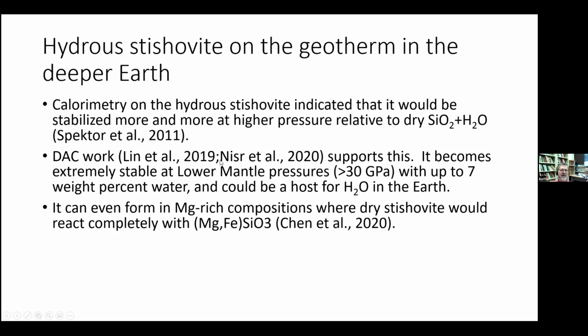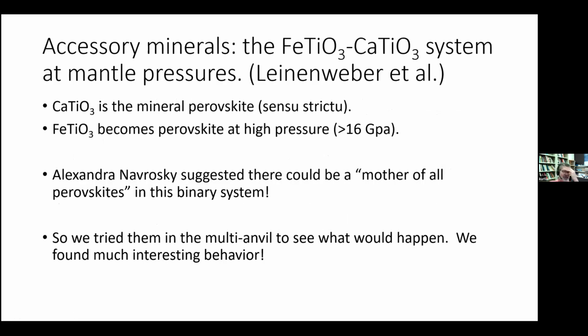high quality samples. The other thing about this stishovite is it forms as a calcium chloride structure, even at 30 GPa with the water in it. And that's low for calcium chloride, but with water, it is stabilized. And when you recover it, it is back to the rutile structure. So it goes from orthorhombic to tetragonal during decompression. And I'm not sure how the crystal quality is. I mean, we get a powder pattern, but so far our peaks are not always narrow. And I don't know if we can get narrow peaks on any of these samples.